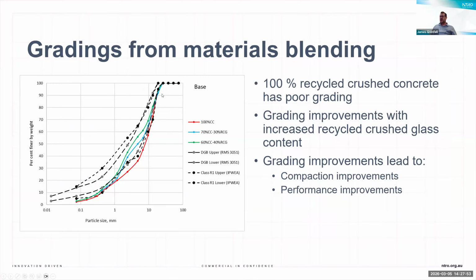So in this case, again, a grading curve, the 100% crushed concrete, you can see has quite a poor gradation, is quite coarse, set at the bottom end of our grading envelope. But by blending with either 30% recycled crushed glass or 40% recycled crushed glass, we can now improve its gradation and get it to sit better within the grading envelope, which obviously then means that there's an opportunity for improved performance. So the potential to get better compaction and through improvements in gradation, and as a function of improved compaction, then improved performance.